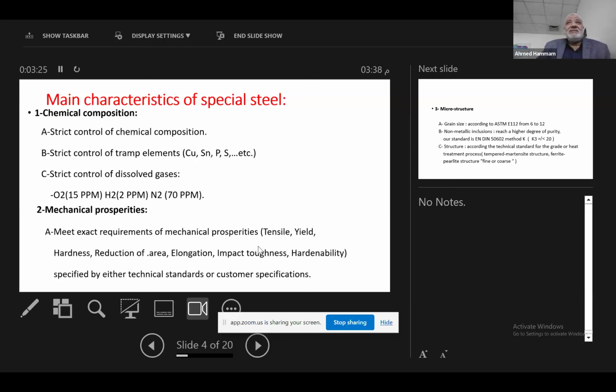So this can answer the question from the person who asked whether we can produce special steel or alloy steel without vacuum degassing. The answer clearly is that it is impossible, unless you make it in the induction furnace by remelting the same steel and casting it in another form. So in order to control the dissolved gases, you have to have vacuum degassing.